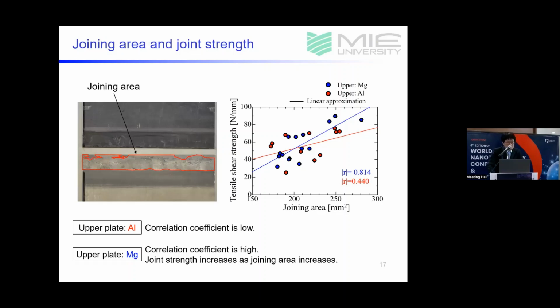When the upper plate was Al, as shown by red marks, the correlation coefficient is low. On the other hand, when the upper plate was Mg, as shown by blue marks, the correlation coefficient is high, and therefore, it was found that the joint strength increases as joining area increases with the upper plate of Mg.